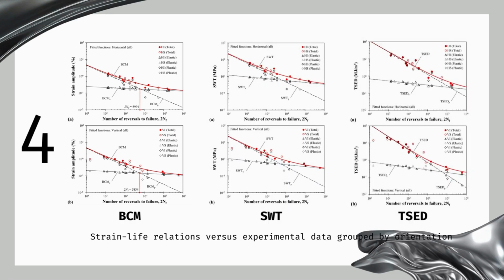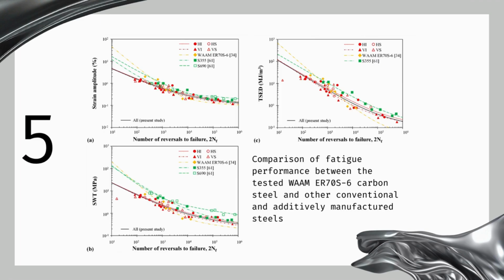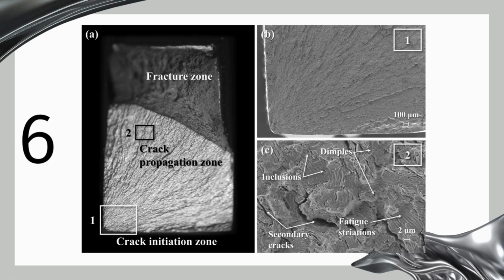The 3 different fatigue prediction models, Basquin-Coffin-Manson, Smith-Watson-Topper, and total strain energy density, align well with experimental observations, with no statistically significant difference. WAAM carbon steel showed inferior low cycle fatigue performance compared to conventional steel. However, it demonstrated consistency with previous literature and exceeded the expected performance in the elastic regime.